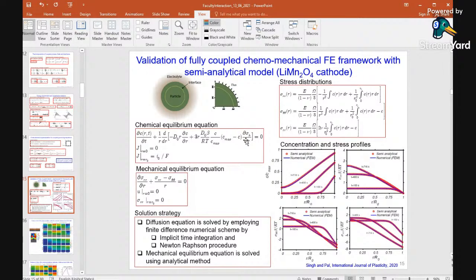In this case, we use a finite difference method to solve this equation, because there is not a standard analytical approach available, because there's a pressure coupling and a stress coupling. Then the mechanical equilibrium equation we solve by analytical method. Our finite element result completely predicts these two solutions. So that's the way we have validated our scheme.